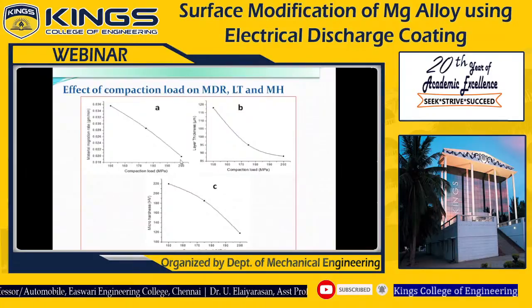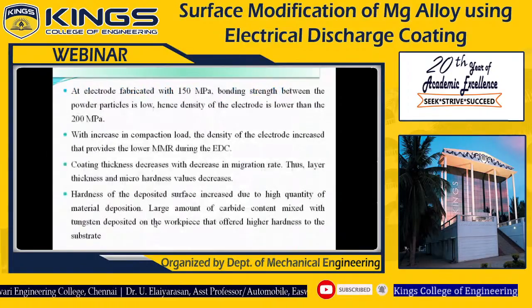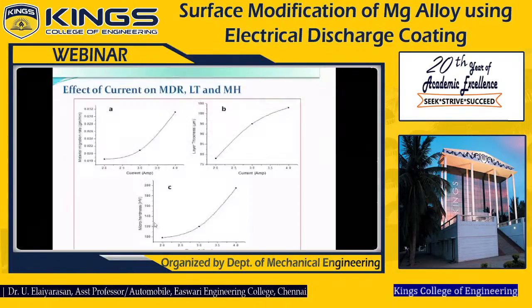Similarly for layer thickness: if a higher deposition rate occurs, the layer thickness will be high. Normally, where the layer thickness is highest, the micro hardness will also be high. So it's normal. The coating thickness decreases with the decrease in migration rate, thus layer thickness and micro hardness values also decrease. The hardness of the deposited surface increased due to the high quantity of material deposition. The large amount of carbide content mixed with tungsten deposited on the workpiece offered higher hardness to the substrate.